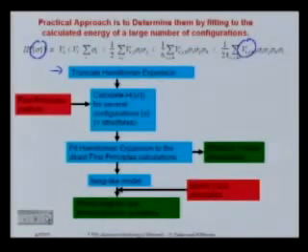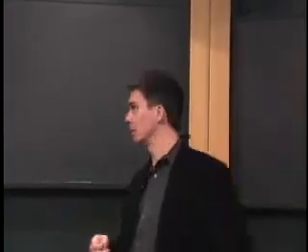So what you can do is literally calculate the Hamiltonian, or in this case the energy, for a lot of these configurations. Let's say there are 20 of these V's you have to determine. Then if you have the energy at 20 different configurations, you could determine the interaction coefficients. Typically, people use very overdetermined sets. So if you want 20 of these, you may do 50 energies and do a least squares fitting, just to make the determination of interactions much more stable. But that's essentially how it's done.